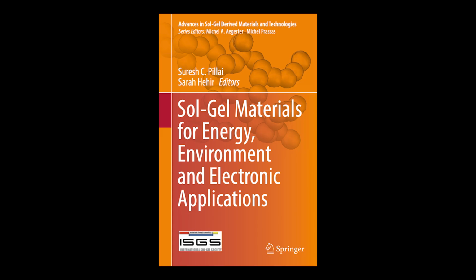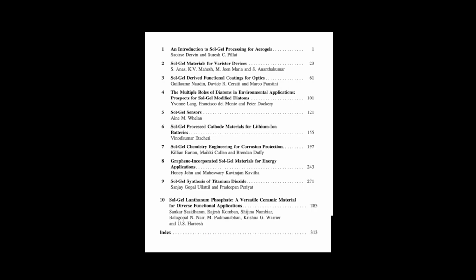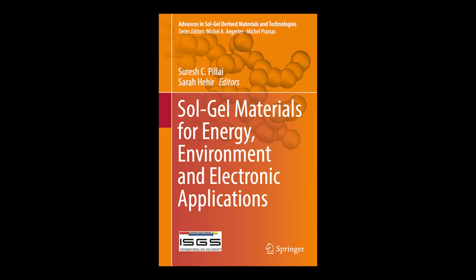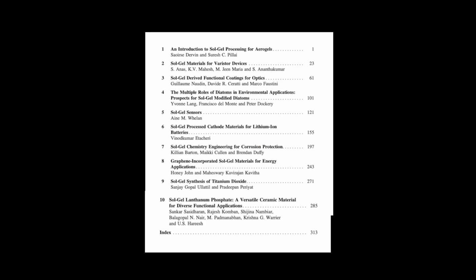Okay, that makes sense. Let's move to some specific gas sensing examples from the chapter, starting with optical detection methods. Sure. Optical gas sensors often rely on changes in fluorescence or absorbance. For oxygen sensing, a common approach is to use the sol gel film to immobilize certain transition metal complexes, like ruthenium polypyridyl complexes. These complexes glow, they fluoresce, when excited by light. But when oxygen molecules are present, they collide with the excited complex and quench its fluorescence, basically turning the light off. The degree of quenching, how much the light dims, directly correlates with the oxygen concentration. And by tailoring the sol gel matrix, say, by making it more porous or adjusting the ratio of precursor and water, you can fine-tune the sensor's sensitivity and response time. Clever. And another optical example.